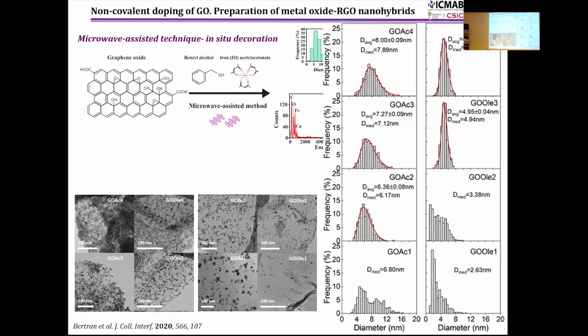But then, even though we are able to change the loading, we have the same problem, and that is that the distribution of the size of these nanoparticles onto graphene oxide is not homogeneous. So we don't have, in general, narrow distributions.